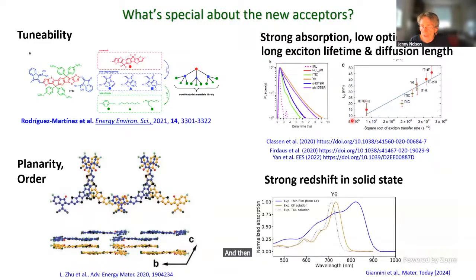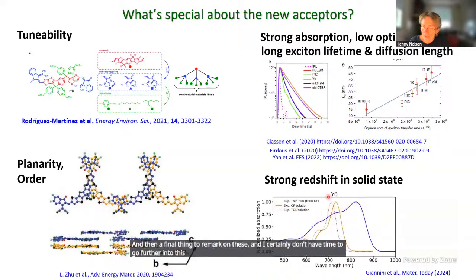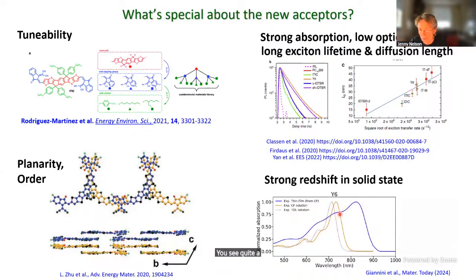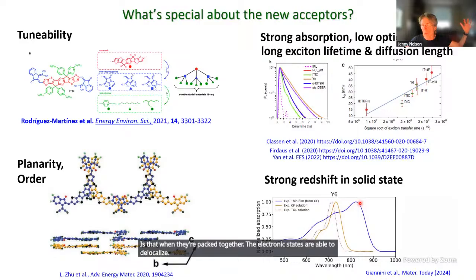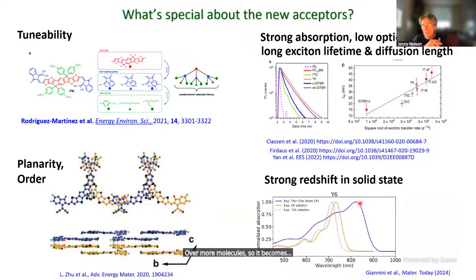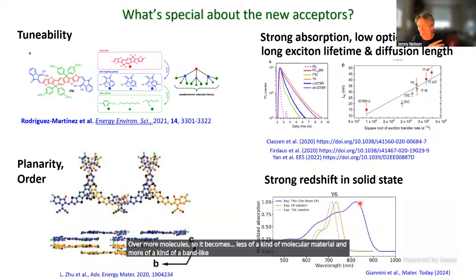And then a final thing to remark on these, and I certainly don't have time to go further into this today, is that once you take a molecule in isolation and pack them together in the solid state, you see quite a significant shift in their optical properties. And what that tells us is that when they're packed together, the electronic states are able to delocalize over more molecules. So it becomes less of a molecular material and more of a band-like material where the electronic states are able to delocalize.